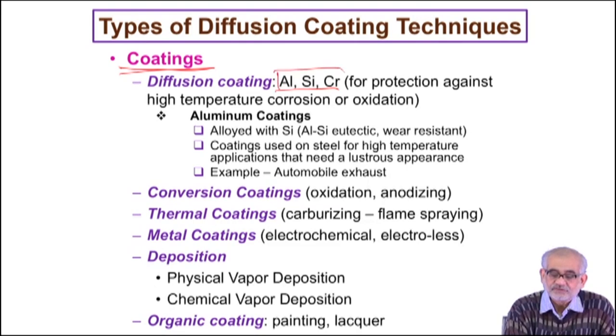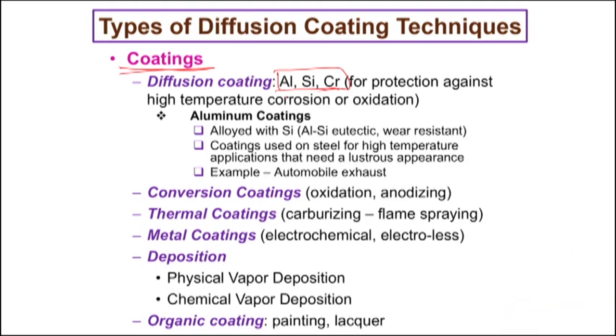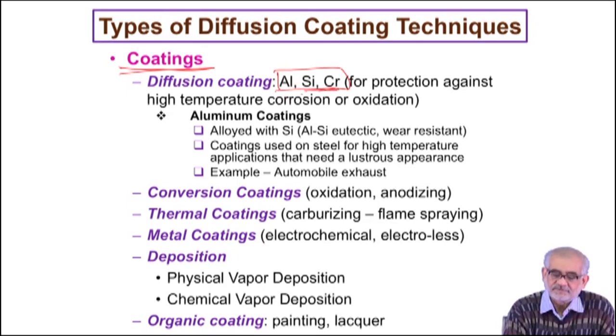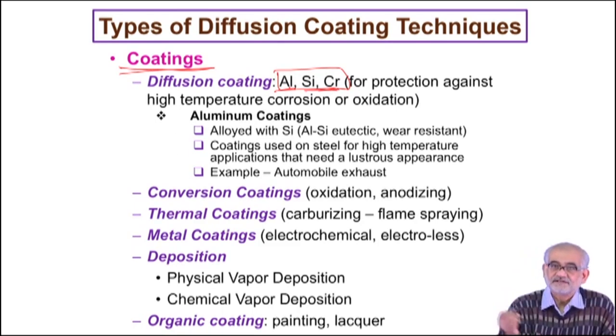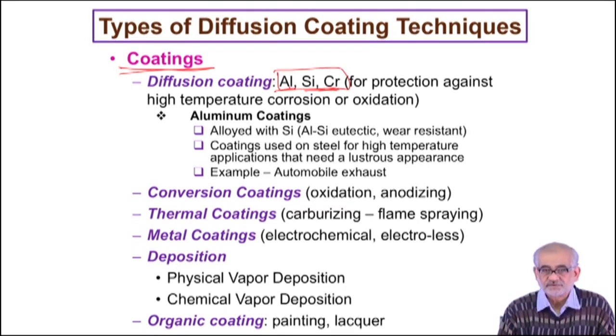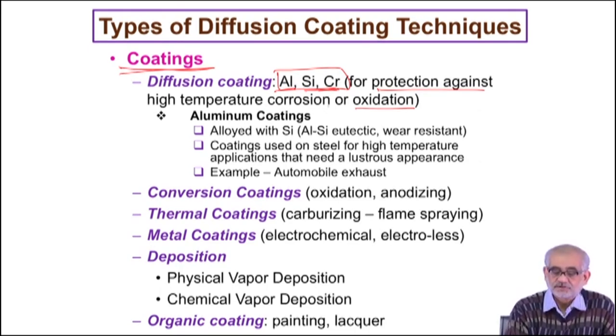This means they form the most stable oxides — if there is competition between some cation and aluminium for oxygen, aluminium will win because it has higher affinity and its oxide is more stable. All the diffusion coatings used to protect turbine blades at 1050 degrees centigrade are therefore based on a coating containing one of these elements, usually aluminium. The aluminium creates an oxide layer on top which protects further ingress of oxygen from the atmosphere into the metal, and as a result further oxidation or loss of metal is prevented. This is how we protect against high temperature oxidation.